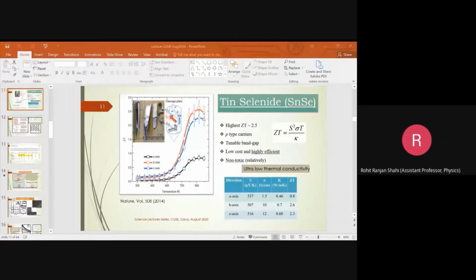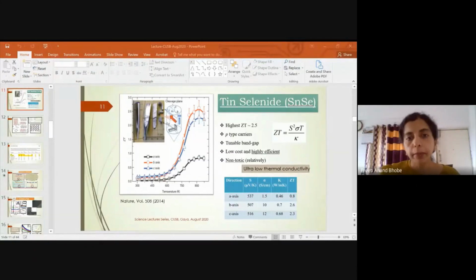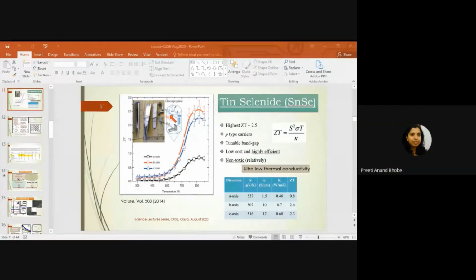I have a question regarding densification. How does densification perform for the nano form of these SnSe? Densification will be similar to what you would do in any other material. It is done like we densify any other oxide pellet. You put some kind of organic binder in this and make a very strong pellet, and you have to anneal the pellet. Is this pellet made directly by hydraulic press? Yes, direct. Hydraulic press will give you a particular densification.